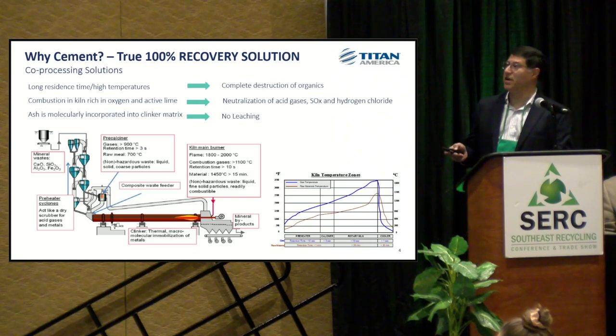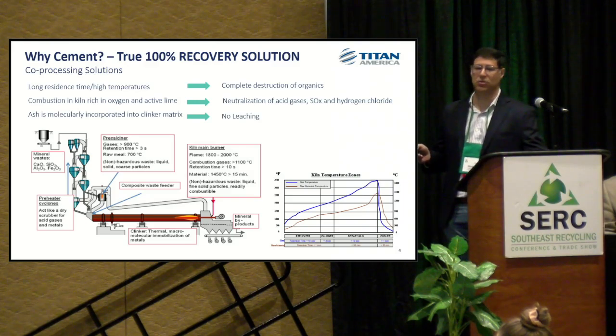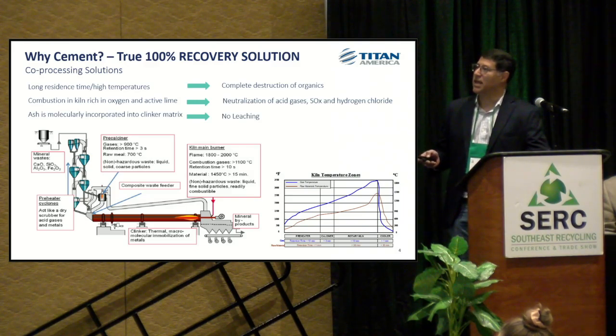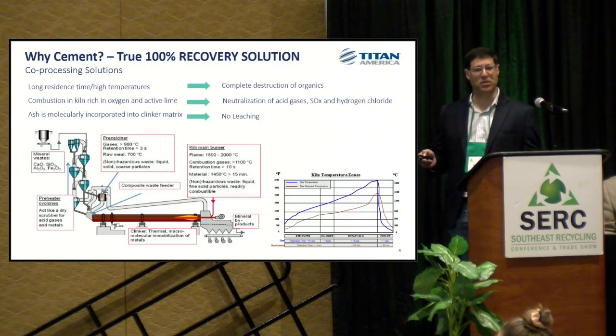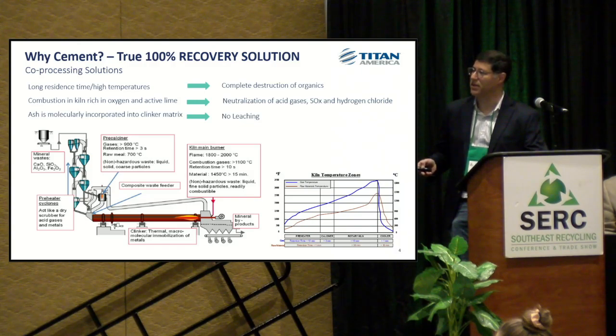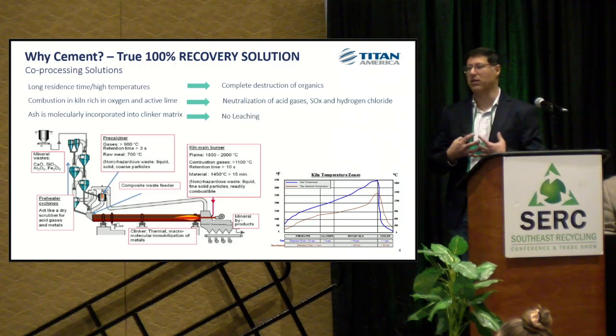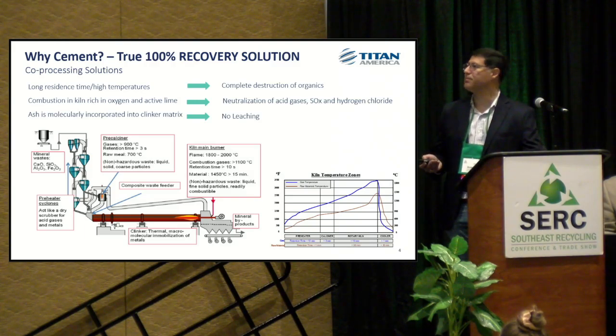Long residence time at very, very high temperatures, so we guarantee the complete destruction of all the organic materials that are there. The combustion is rich in oxygen and active lime, so it's a very alkaline environment, so we are able to neutralize any acid gases, SOx, or hydrogen chloride that might be in the system. And one of the most important ones is that the ash is molecularly entrapped or incorporated into the clinker matrix. The clinker is the product that comes out of this little tube here, and it is completely molecularly entrapped, so no leaching. No matter how fine we crush that material, it is never going to leach.